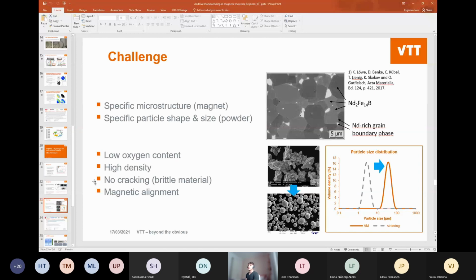But the challenge is that to get the high properties, you need a specific microstructure. And actually here, the best microstructure is what the sintering process is tailored to do. So what you want is equiaxed grains which are surrounded by a neodymium-rich grain boundary phase. And if you remember from, for example, Olli's presentation, the microstructure that you get after laser powder bed fusion is totally different, and this is not optimal for this material. So this is one challenge. So how can we create a structure where each of the grains is surrounded by this, so to speak, insulating neodymium-rich grain boundary phase.